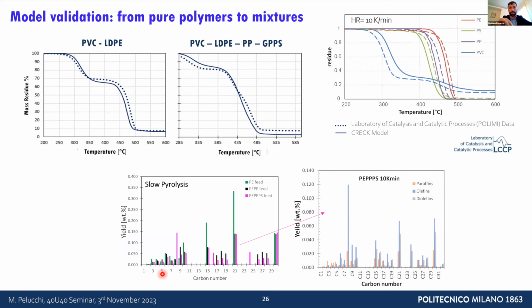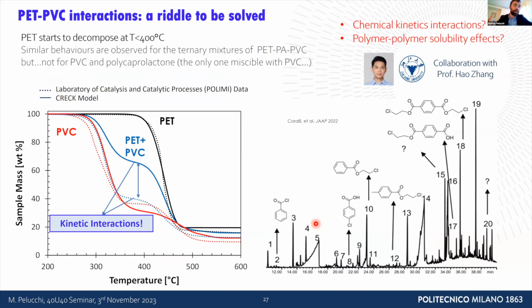Of course, there are some species in carbon numbers that are not represented. This is due to the lumping approach, and we can look at the feed effect, the heating rate effect, the temperature effect, and so on. But things are not all good. If we look, for example, at PVC and polyethylene terephthalate pyrolysis, we see something very different from what we've seen in previous polyolefins-only mixtures.